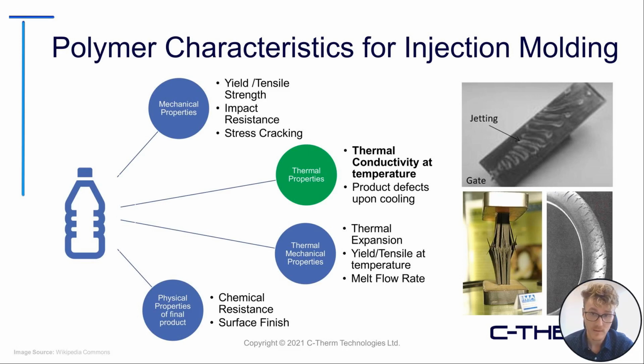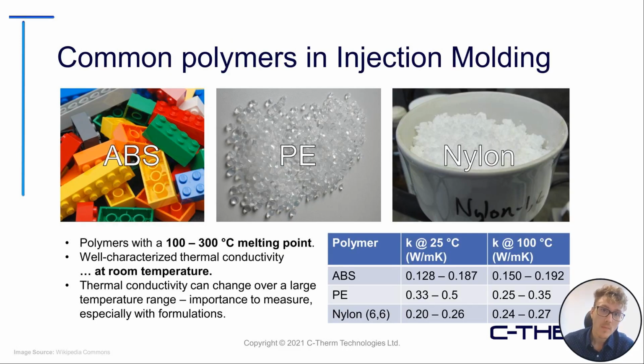Thermal conductivity can become a proxy for you to model these types of defects and how to minimize them during a process development standpoint. Some of the common polymers that are used in injection molding are ABS, high-density polyethylene and low-density polyethylene, and nylon. And while these polymers are well characterized at room temperature, as the material becomes higher and higher in temperature during the injection molding, the thermal conductivity does decrease or increase depending on the polymer. And with polymers that are reaching towards the melting point of around 300 degrees Celsius, we need to have a method that is able to determine thermal conductivity at these higher temperatures.